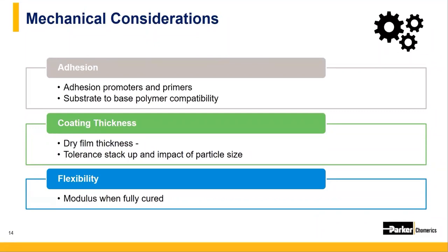So on that, coating thickness is referred to as a dry film thickness because the paint thickness is measured once all of the solvents have been evaporated off during the curing process. Coating thickness is impacted by particle size as well as the accuracy of the painting process, and in addition to the surface protection qualities of the recommended thickness of the paint, the coating thickness also has an impact on the electrical properties and really should be measured and validated to ensure proper performance. And finally, different binder systems will have varying levels of flexibility. Some applications will have unique and complex geometries that will require less viscous paint to fill in tight angles and small crevices.